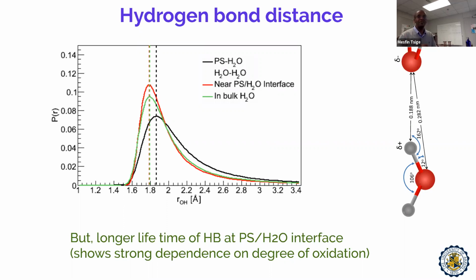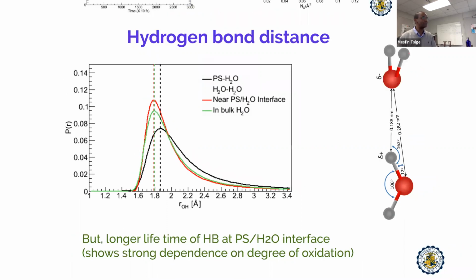But in general, we didn't see much observable dependence that would account for shifting the melting temperature. Whereas when we look at the distance between the hydrogen bonding of the water with the substrate, we tend to have a larger ROH value. So a water molecule has to break bonding with another water molecule to form a hydrogen bond with the substrate. Which means at least one part of the hydrogen bonding has shifted. That should have some consequences in the physical properties of the water close to the surface.